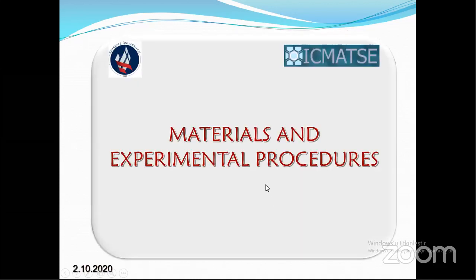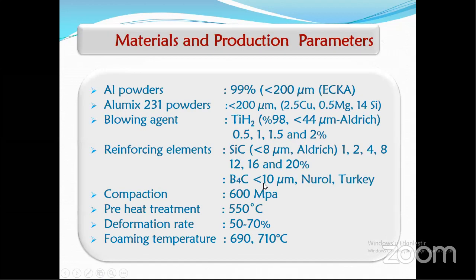You are cutting a rectangular shape foamable precursor. Because of surface tension, it turns into a spherical shape. If you have a very big material, the bottom side is a little bit flat, but nowadays we prepare a special mold for this, so we can get very nice, very spherical samples. I will show some materials and the experimental procedure for those materials.